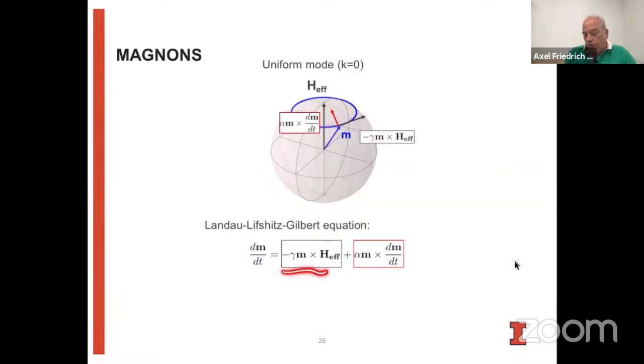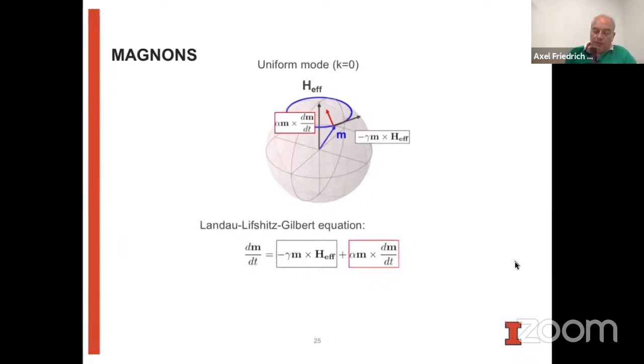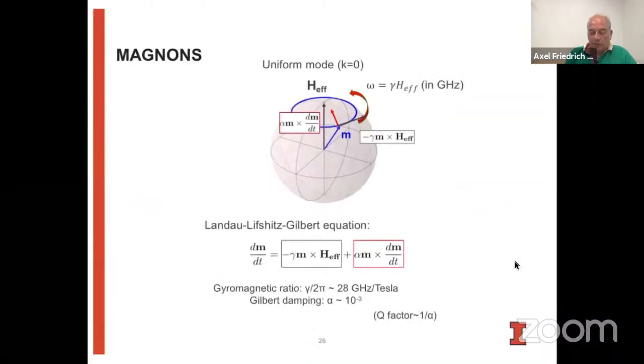And so the torques work like this: the precession torque is tangential to this precession direction, and this damping torque will decrease the size of the precession cone angle. And so the precession frequency is then given by the effective field. And we know that this corresponds to pretty much 28 gigahertz per Tesla. And the magnetization damping that we have in good magnetic systems where we want to look at the magnetization dynamics is of the order of 10 to the minus 3, or maybe lower if we have really good systems. And so we can define the quality factor for a magnetic oscillator as 1 over the magnetic damping.